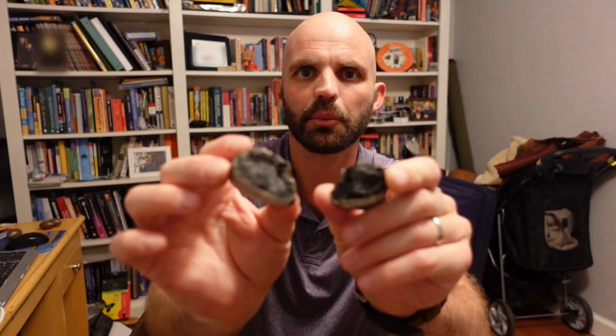I hadn't done any testing on it. I just went full power, about 20 minutes, stuck it in there, and it turned into this. It went from this shape to this shape. Completely sagged, vitrified the surface, looks like a turd, and I took a hammer to it and broke it apart because I wanted to see what was inside it, but it went completely densified except for a few bubbles and just sagged. This probably got up to 1500 Celsius or something. So yeah, you can melt clay, and that's something you have to worry about when using the microwave kiln, especially when it's a 1200 watt microwave.